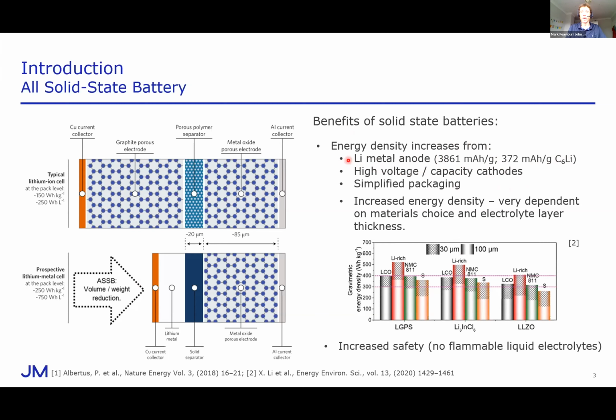And once you combine a lithium metal anode with high voltage, high capacity cathodes, you can achieve some significant advances. So, back to materials choice. This chart was taken from reference 2, and it shows how materials choice and chemistries clearly have a huge impact on gravimetric energy density. For example, take this sulfide material, lithium germanium phosphorus sulfide, a thiophosphate even. If you combine that with this cathode material in red, in its thinnest form, a 30 micron layer, you can achieve energy densities in excess of 500 watt hours per kilo.